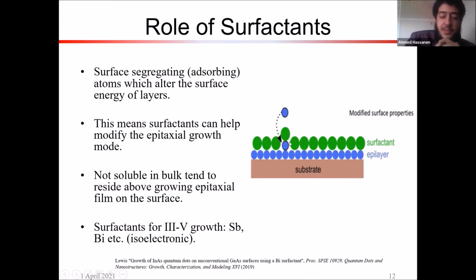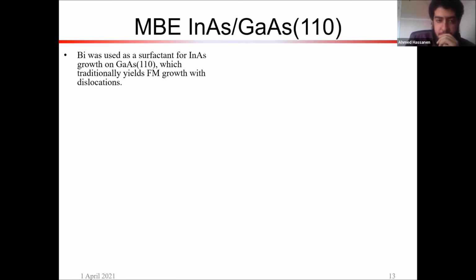A key thing to note is that we don't want surfactants to be soluble in the bulk. We want them just to float on top of the layer being grown. And then once the growth is finished, we want them to dissolve or evaporate from the surface. The most famous surfactants for III-V growth are antimony and bismuth, and basically, that's what we'll be using in the research.